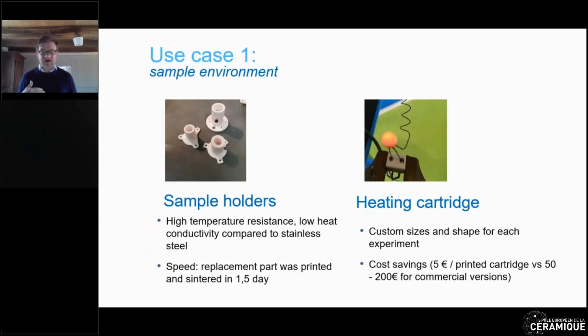If you focus on the 2 first ones, which are already actually being used by ESRF, they're really being used for actual measurements. Sample holders, it's quite simple. They started because they had an experiment where the sample holder was in stainless steel, and they had a problem of heat conductivity. The stainless steel was too conductive, which meant that the samples were not at the targeted temperature. By replacing with ceramic, they managed to solve that problem, but they needed the replacement part very fast. Because the measurement was already going on, they managed to reduce the part production between design, printing, binding, and sintering to 1.5 days before they could replace a stainless steel part with a ceramic part.